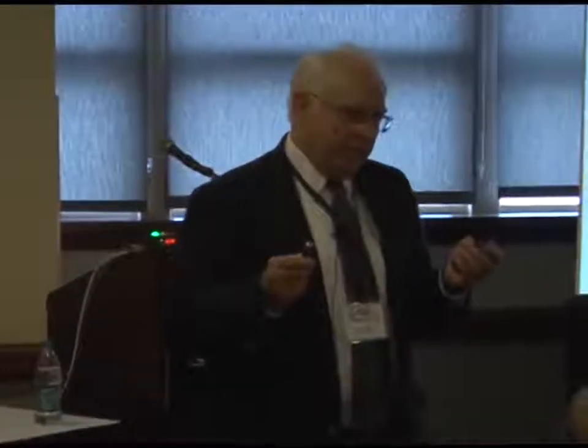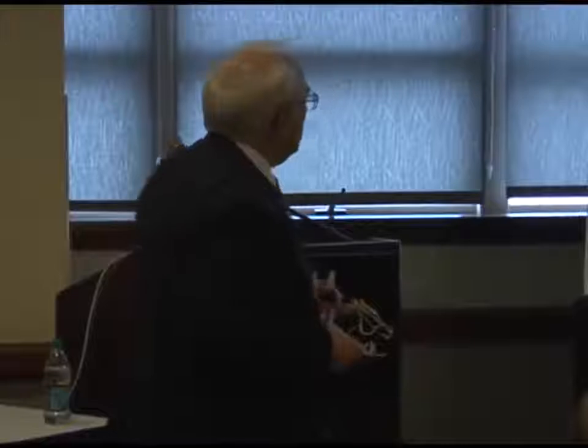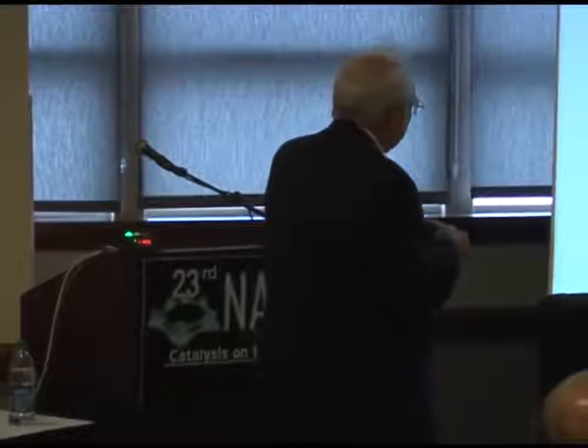So the long and the short of it is that by reducing the average distance between rhodium and iridium by 3 orders of magnitude, we have essentially suppressed the dimerization catalyzed by the rhodium. I don't have time to show you all the data. So cartoon-wise, what's happening when we have rhodium alone is that somehow we have ethylene bonded to the rhodium, and nearby, this is very cartoonish, we have ethylene bonded to the hydroxyl groups of the zeolite, and somehow we get carbon-carbon bond formation.